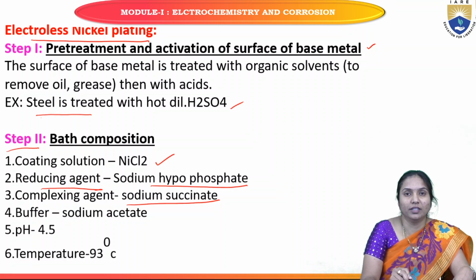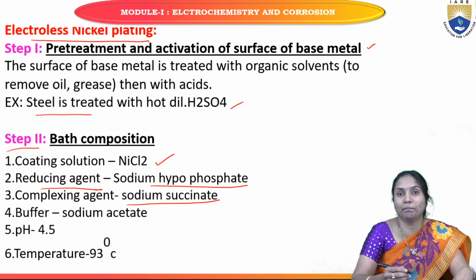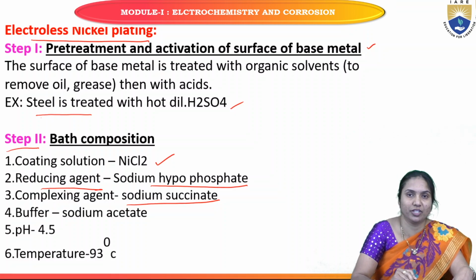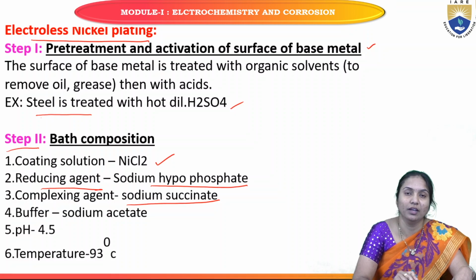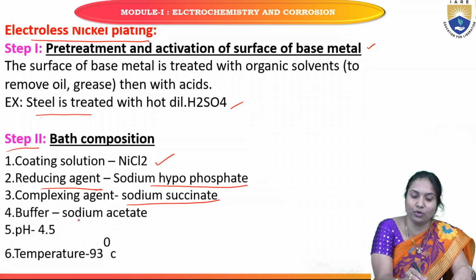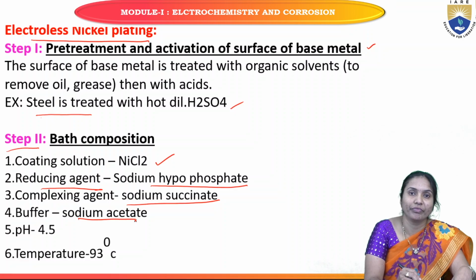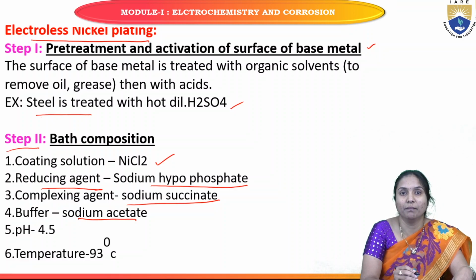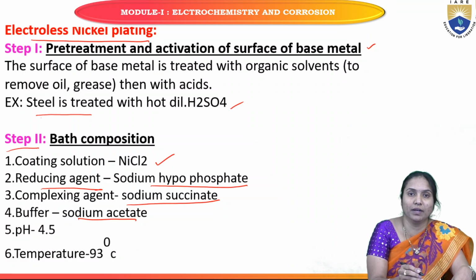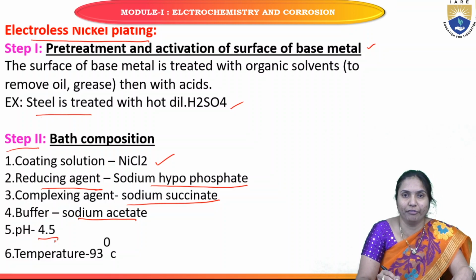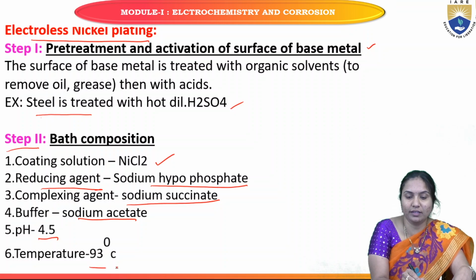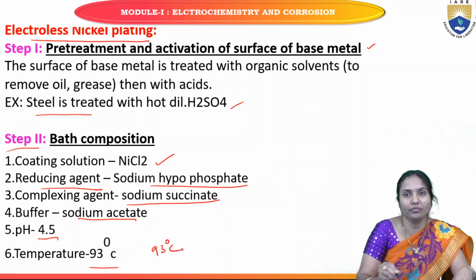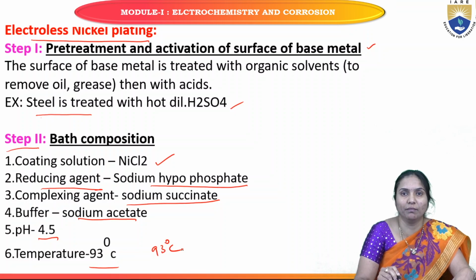And buffer, generally we use a buffer to maintain a stable pH range. For that purpose we are using a buffer solution. So here the buffer solution is sodium acetate. Sodium acetate is used as a buffer solution maintaining a stable pH range. So in this coating we maintain a pH of 4.5 and the temperature is 93 degrees centigrade. So this is the preparation of the coating bath.